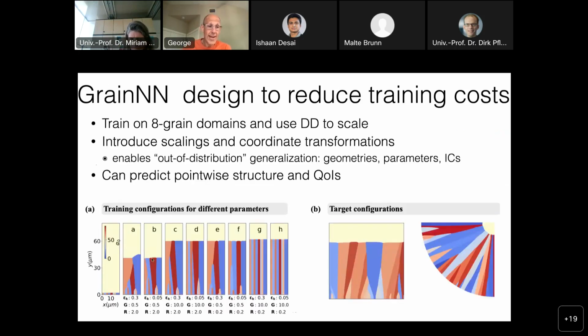So the main idea is to actually train on a small 8-grain domain. So when I say 8 grains, we have 8 grains in the substrate, which is really tiny, on a very simple rectangular domain, and then sample our inputs. So we will be sampling the grain distribution right here, the initial condition. For example, what is the orientation and what is the size of the grains right here. We're going to sample this, the heat transfer and the material properties, and then we're going to have different data sets in which we're going to use as ground truth to train a reduced model.